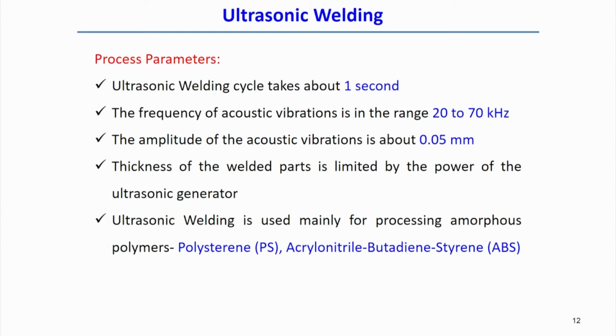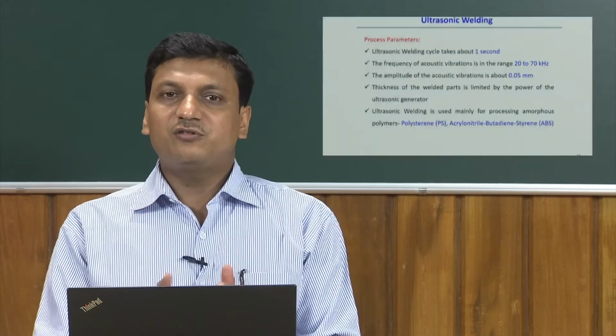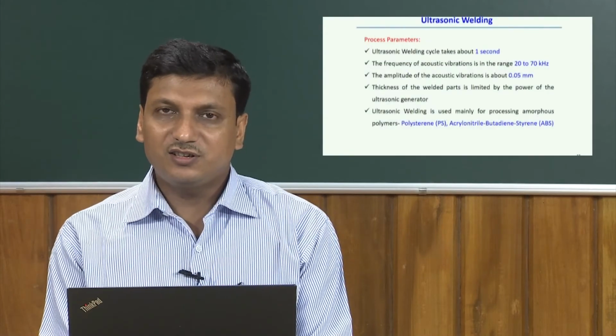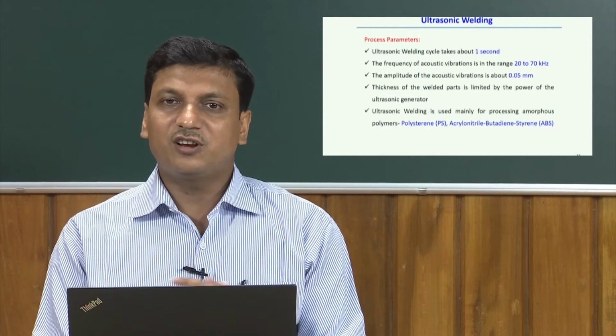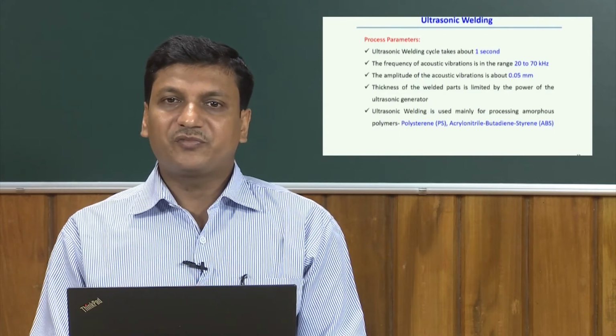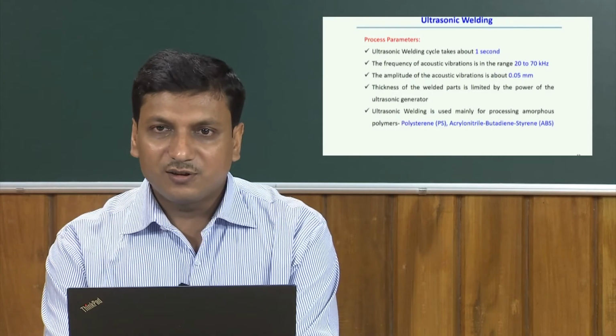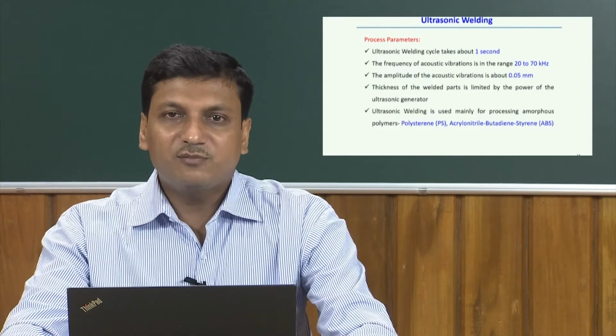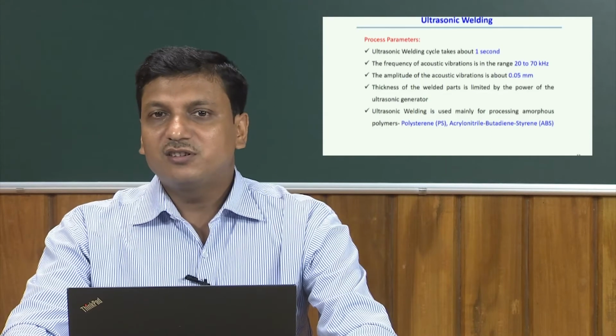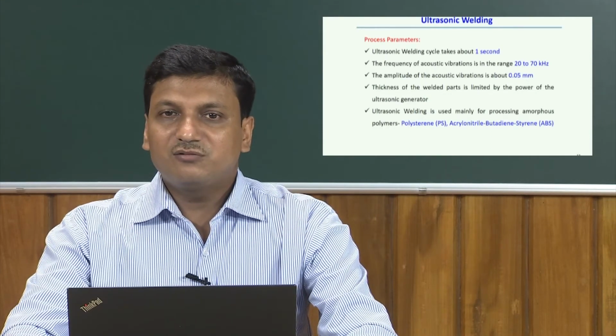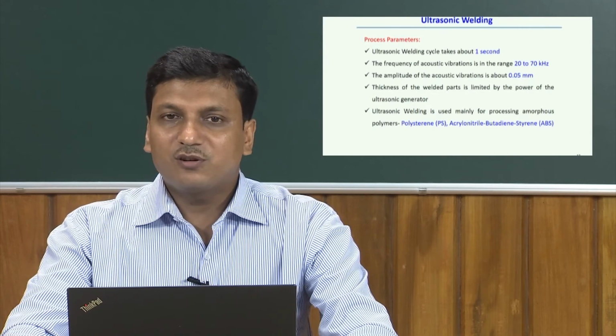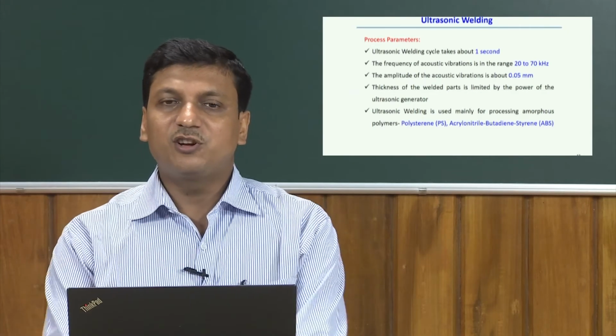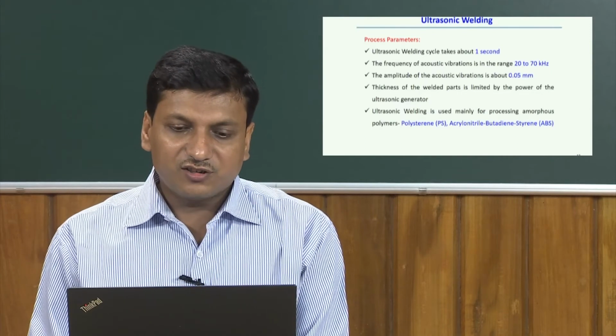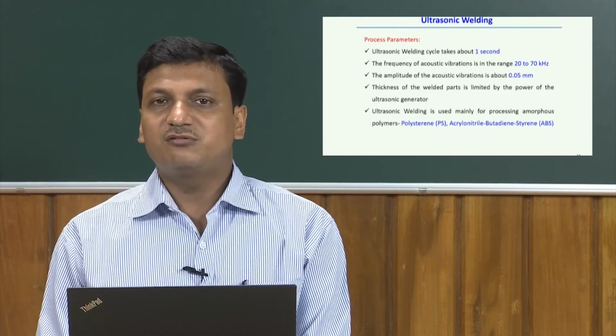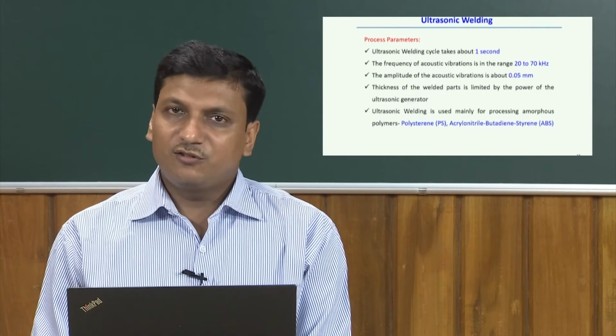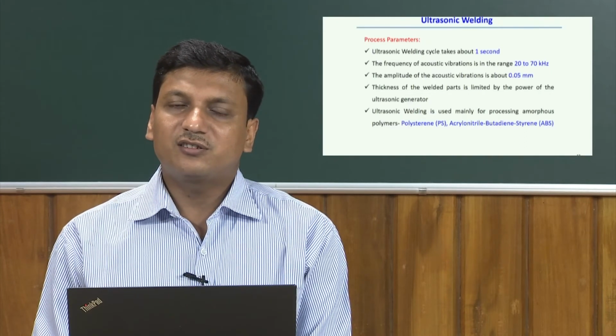That is why the affected zone of the very localized frictional heat energy is very small. Therefore, the thickness of the plate welded is normally small, but it is decided by the power of the ultrasonic generator. Ultrasonic welding is mainly used for processing amorphous polymers, for example polystyrene (PS) and ABS. This kind of polymeric material is normally welded using ultrasonic welding processes.